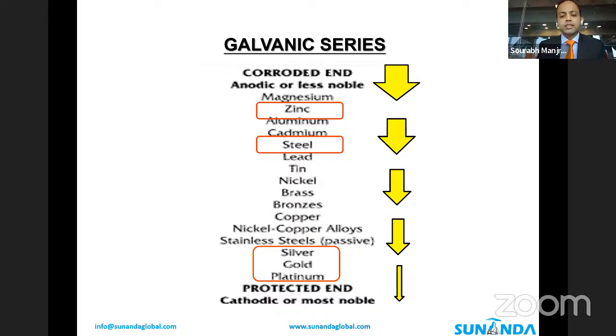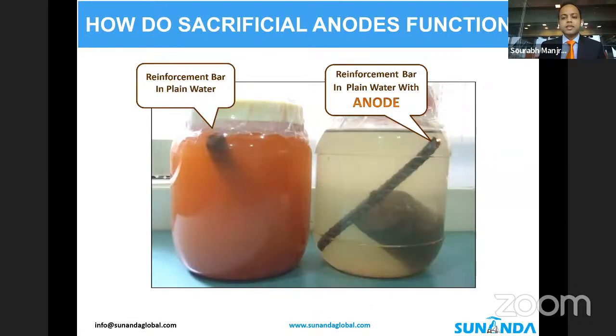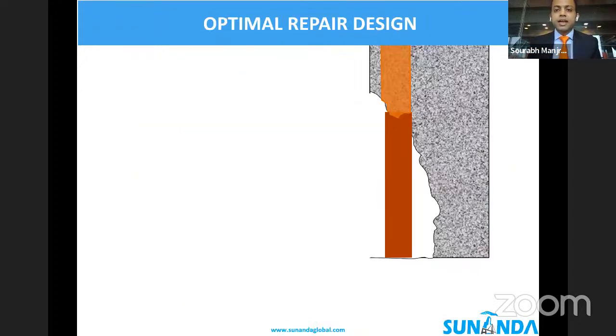So in the oxidation reaction of steel or the corrosion reaction of steel, zinc will corrode first, steel will corrode second, and silver, gold, and platinum will not corrode. What we have done is developed zinc alloy-based sacrificial anodes. So if you take a look at the jar on the left-hand side, there's a rebar in that, which is in plain water, and the rebar has started corroding. In the jar on the right-hand side, another rebar, also in plain water. However, the sacrificial anode has been connected to this rebar and in turn now become part of the electrochemical cell. So whenever corrosion strikes, when the oxidation starts, the zinc alloy will corrode, sacrifice itself, and in turn not let the steel rebar corrode. So how does this help in optimizing our retrofit design?